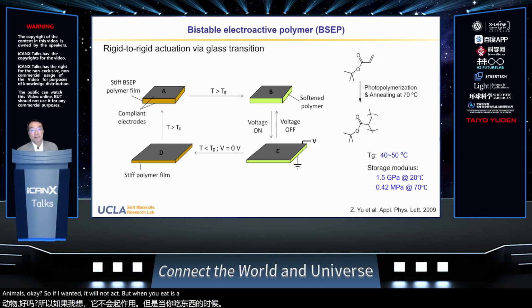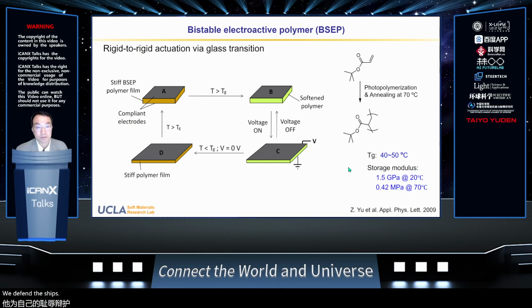But when you increase the temperature above its Tg, to 40 to 50 degrees Celsius, the film becomes rubbery. Now at the operation voltage, the film will expand just like the dielectric elastomer. If you maintain the voltage and let the film cool down, it becomes stiff again. Now you remove the voltage, and the film will not shrink back. To go back to the original shape, you simply heat the film up without a voltage applied. So this BSEP film offers bistable deformation to different shapes through a combination of heating-cooling cycles and the driving voltage.